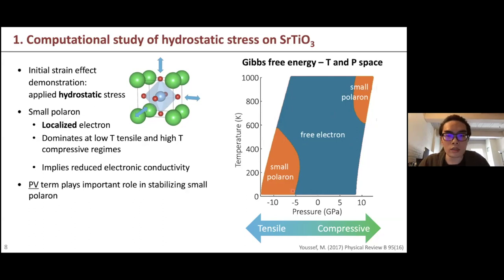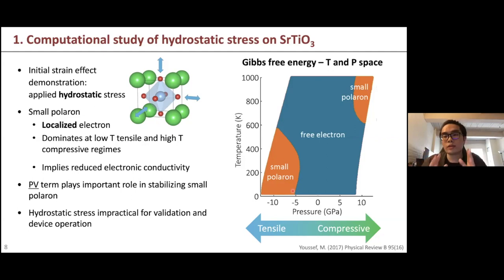And since we use the Gibbs free energy, because that's what we control in the simulation, the pressure times volume term is very important in stabilizing the small polaron. However, hydrostatic strain is very impractical to do in experiment. As you can see, you have to create around 5 to 10 gigapascals on the material, which is definitely not going to happen in a real experiment. For a thin film, we can create large enough strain to see some changes.